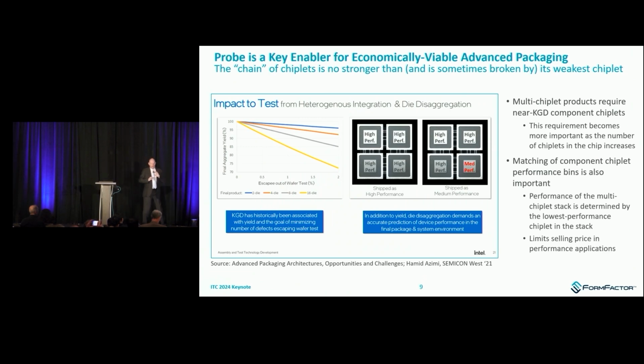Okay, so here's another slide I borrowed from Hamid Azimi. It's getting a little bit old, but I think it's the most straightforward and compelling explanation of why test is important for advanced packaging. The graph on the right is based on some very simple arithmetic and essentially plots the number of escapes you have out of wafer yield, so the gap to known good die, the number of bad die you have coming into assembly, against the final aggregate yield, essentially the final test yield, for a variety of chiplet configurations: a single die, or 2 die, 4 die, 8 die, 16 die.